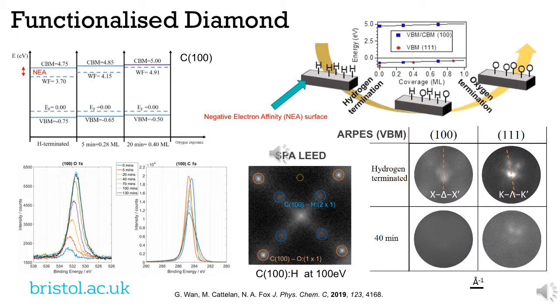The report published in the Journal of Physical Chemistry C demonstrates how we have made full use of the NanoESCA platform to study and visualize step-by-step changes in the electronic and morphological structure of single crystal diamond surfaces, and also to measure the intermediate stages of functionalization, changing from hydrogen to oxygen termination.